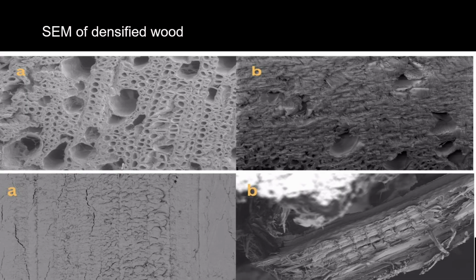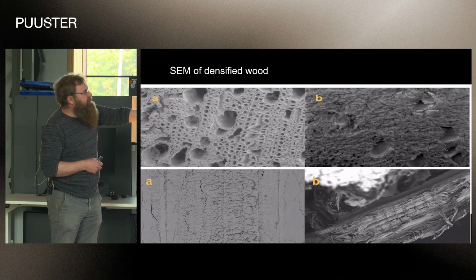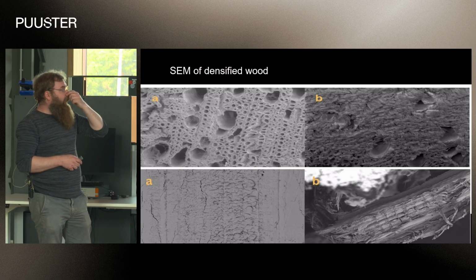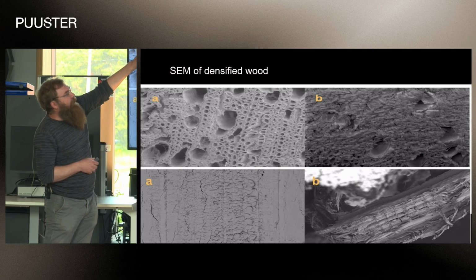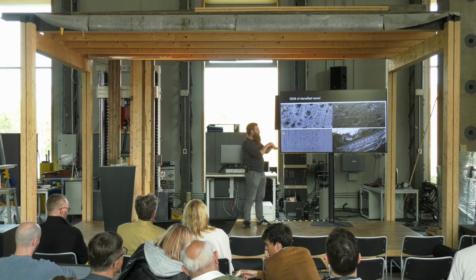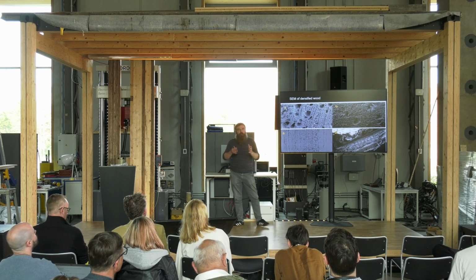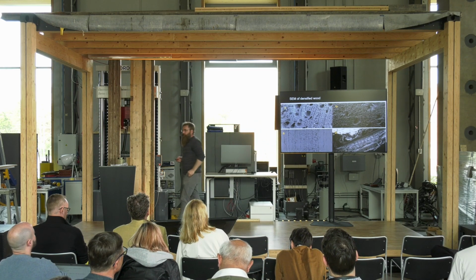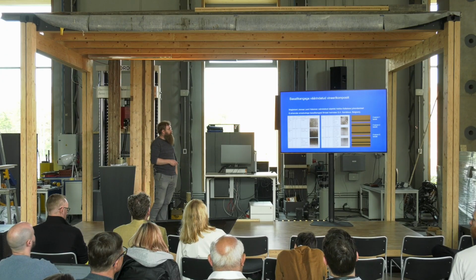We looked at what happens with the densification underneath the microscope. We have here the raw wood sample. We have here the sample where we have washed out some of the lignin, and this is a microstructure of the hardened and densified, I think aspen sample was this one image. We see that all the cell walls are crushed together. They have formed a monolith, which is way stronger than it was before.